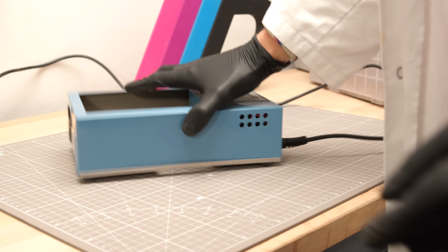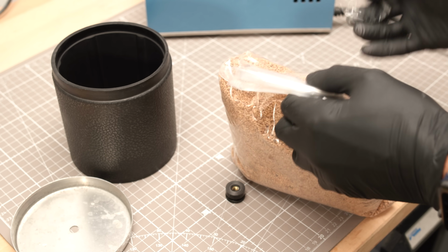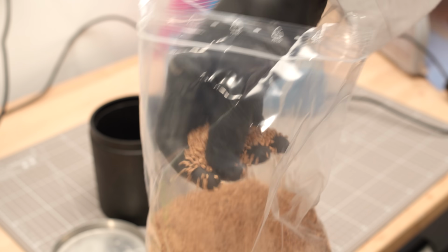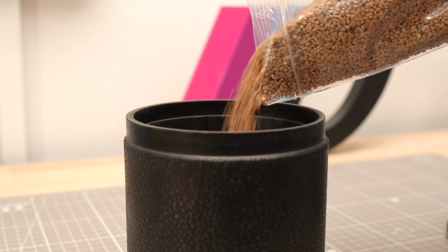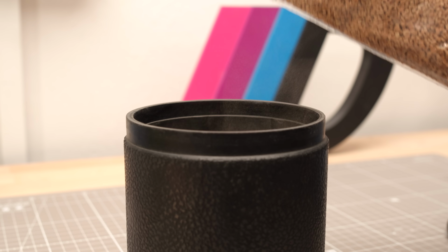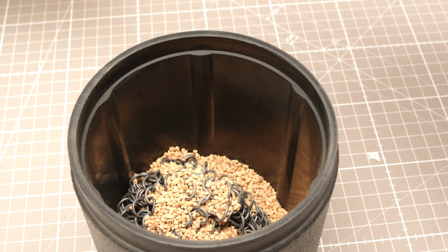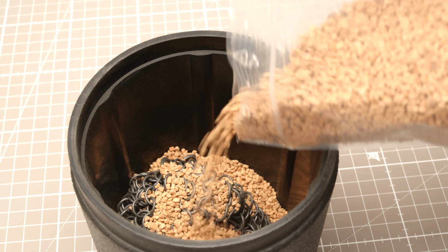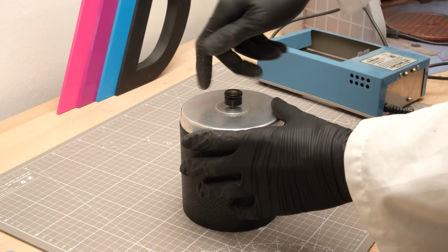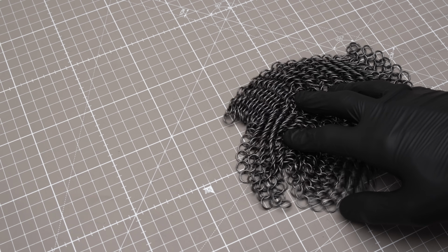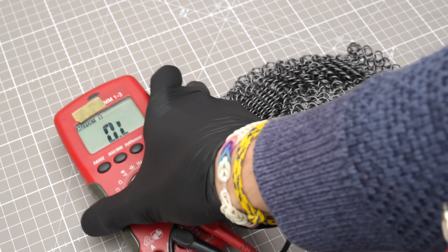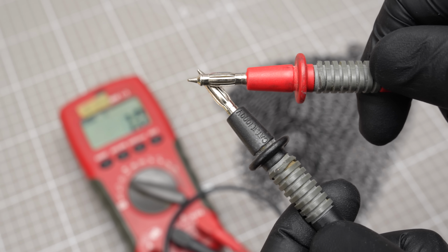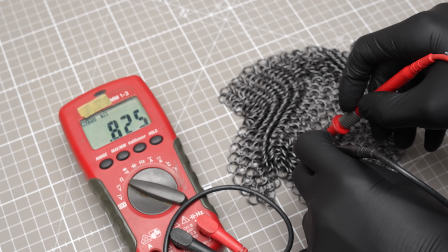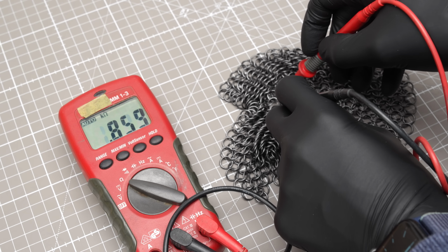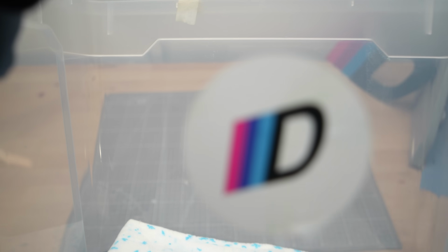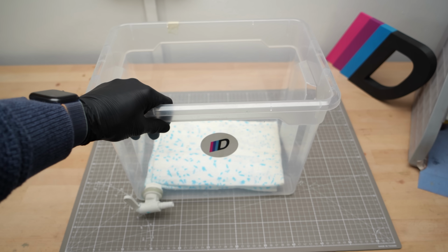I got an idea. Time to bust out the tumbler again and fill it with some coarse walnut shell media. That might give the surface a nice long polish. So, in goes the media, toss in the chainmail, maybe a bit more, close it up, and off we go. Let the wild ride begin. I took it out after about 3 hours and measured the resistance across roughly 2 to 3 centimeters. That might actually work. Now I'm setting up my electroplating bath.